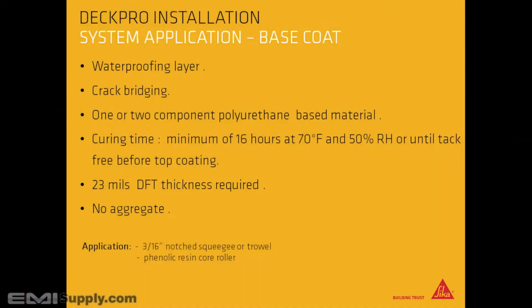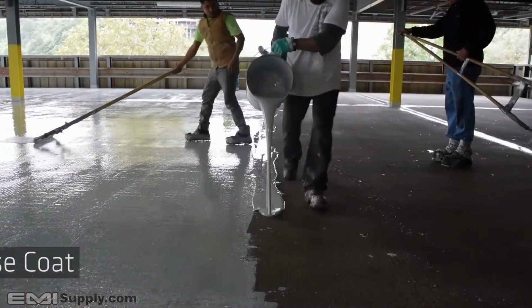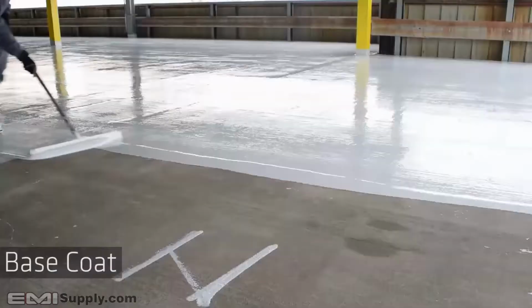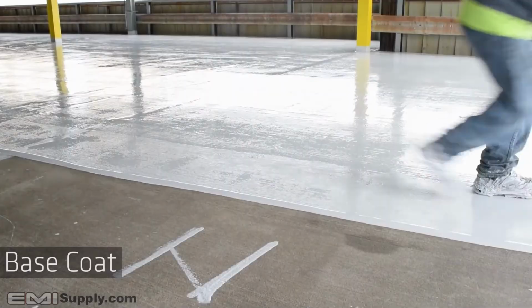Base coat. This is the waterproofing layer. Crack bridging. 1 or 2 component polyurethane base material is used. Curing time for the base coat is a minimum of 16 hours at 70 degrees Fahrenheit and 50% relative humidity, or until tack-free before applying top coating. 23 mils DFT thickness is required. Do not apply aggregate to the base coat. Apply using a 3/16 of an inch notched squeegee or trowel and a phenolic roller. Extend base coat over entire area, including previously detailed cracks and control joints.